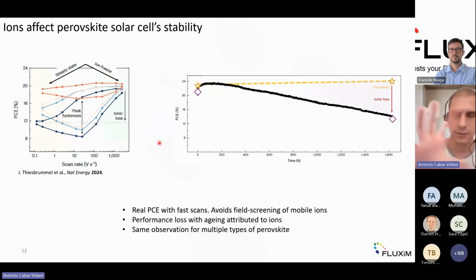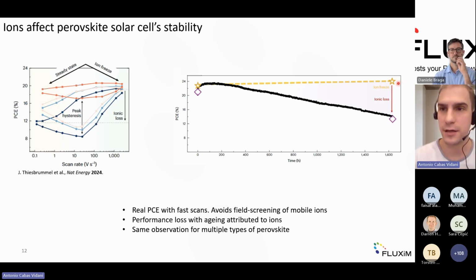So what she did was age a perovskite device. In this very specific case, she considered multiple types of perovskite absorbers. And she noticed that after the degradation, after about 1,600 hours in this case, the measured PCE as obtained from the MPP tracking was way lower than the starting point. But if you perform a JV with a fast scan, so ion-freeze conditions, then the PCE is essentially recovered, or it's actually not lost. So this really indicates the importance of mobile ions on performance measurement and on the stability itself of the perovskite.